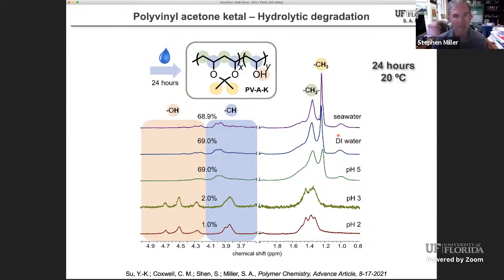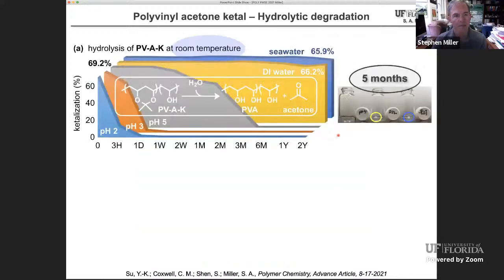So the ketals are surprisingly stable under even pH 5 conditions, maybe a little bit surprising. So we did a longer term experiment. So a day is a day. It's just a day in the life of a graduate student, but let's try this for longer. So on the left-hand side, we see our fairly acidic conditions, pH 2 and pH 3. And as I mentioned, after a day, we see essentially complete hydrolysis of these polyketals.